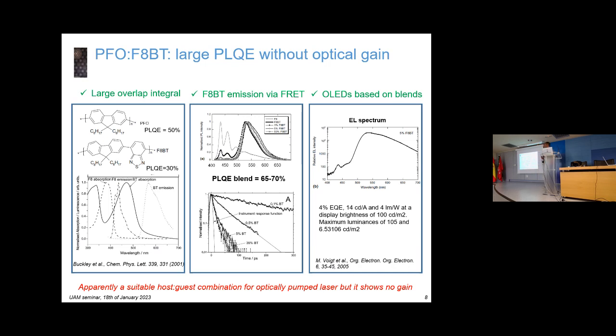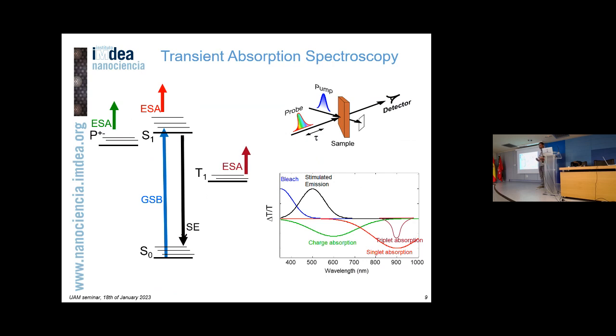But there is an intrinsic fact about this system: in these films with such high photoluminescence quantum efficiency, there is no optical gain, even though the two materials individually exhibit optical gain—so they lase on their own. When I put them together, I cannot get stimulated emission. To understand why, I would like to first introduce the technique we use in our lab, which I'll talk about quite a lot in this talk: transient absorption spectroscopy.